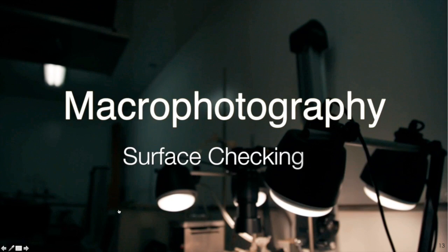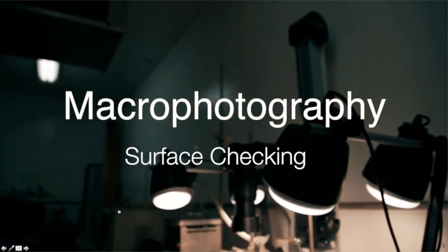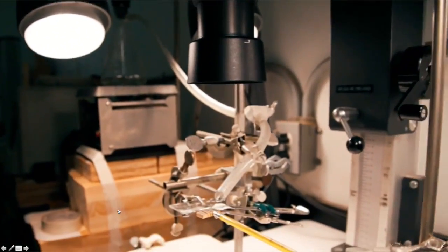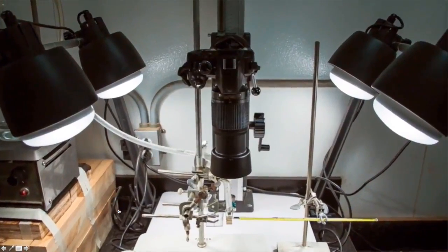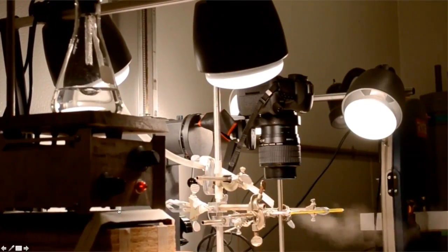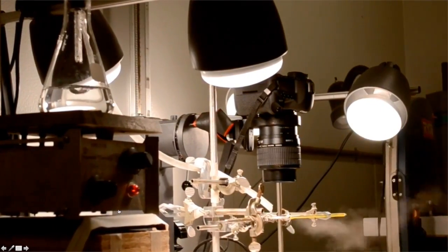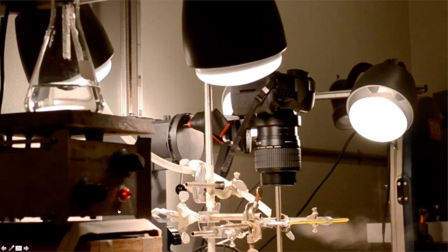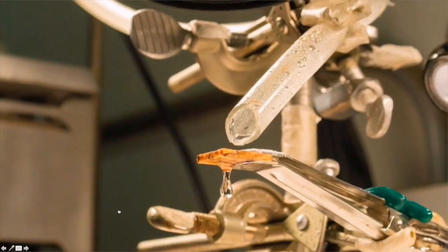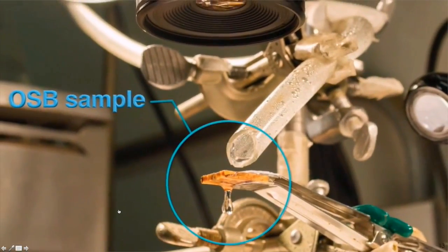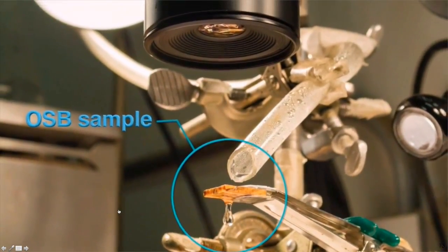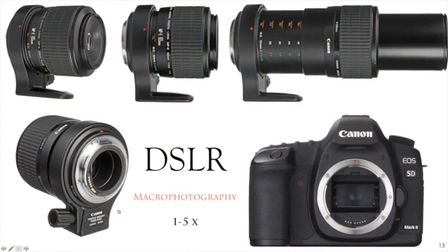So the first technique to look at surface checking is where we employed macrophotography. We developed this device in-house. It is composed of a system that blows moist air for 2 hours to promote wetting, causing swelling, and dry air for 2 hours, causing shrinkage. The system allows high-resolution imaging of OSB through a macro lens that goes from 1 to 5 times magnification.